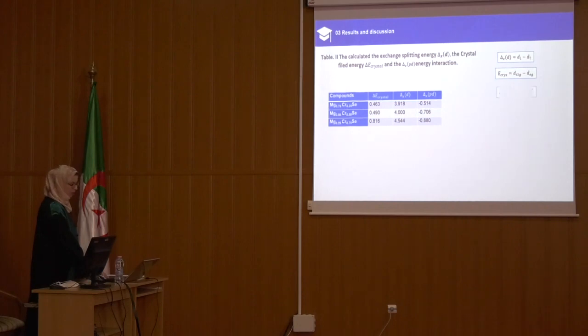We also calculated the p-d exchange interaction energy, according to table number 2. We can see that the values of the p-d coupling are much higher than the crystal field energy. These results confirm the presence of ferromagnetism in these compounds.